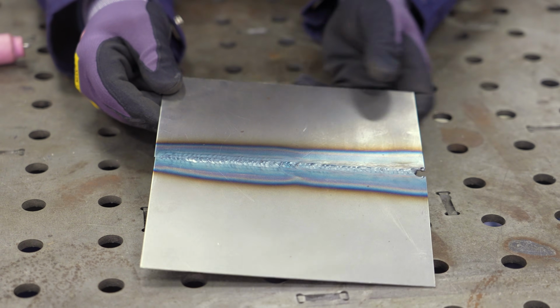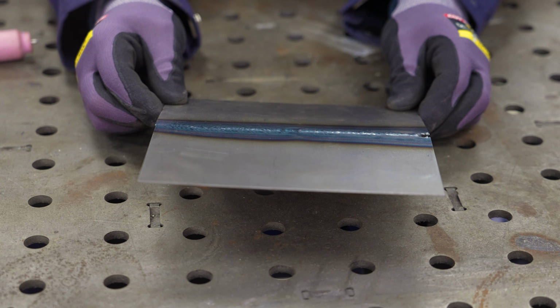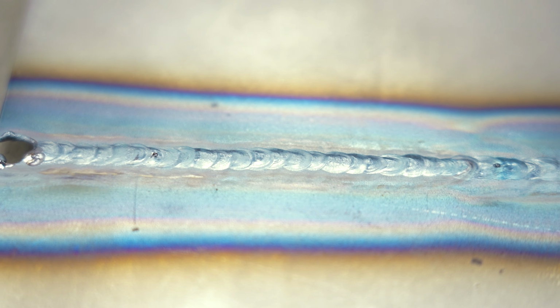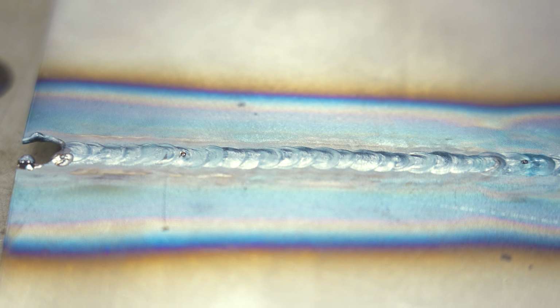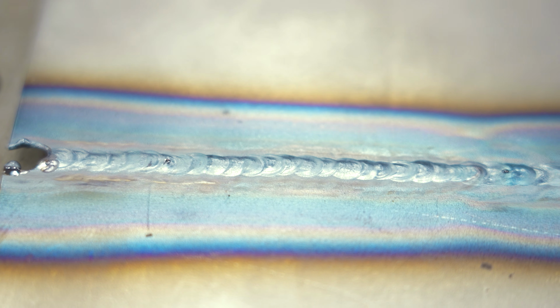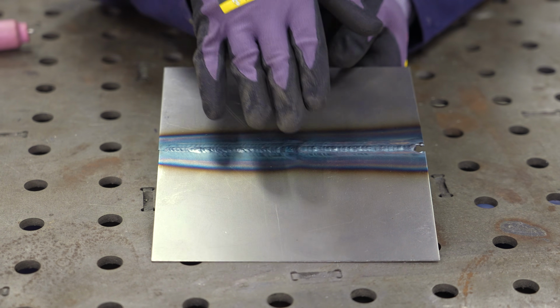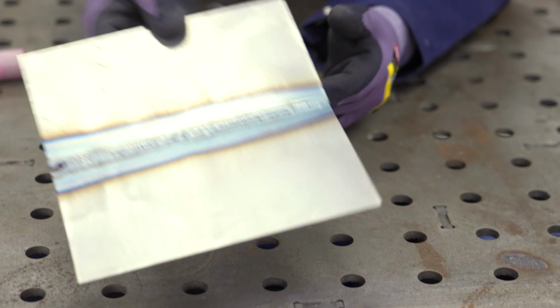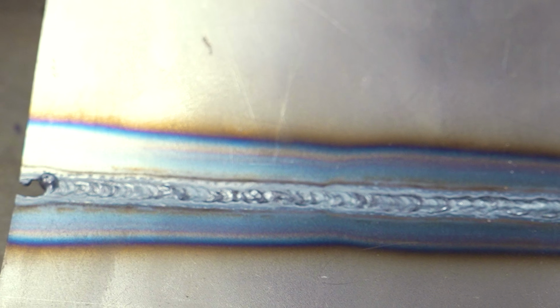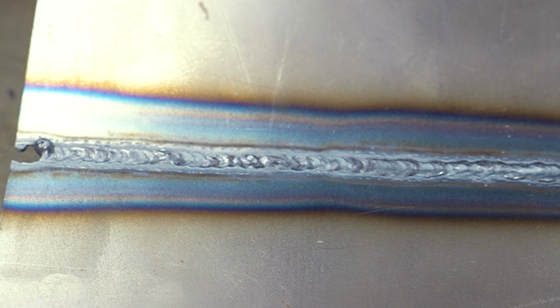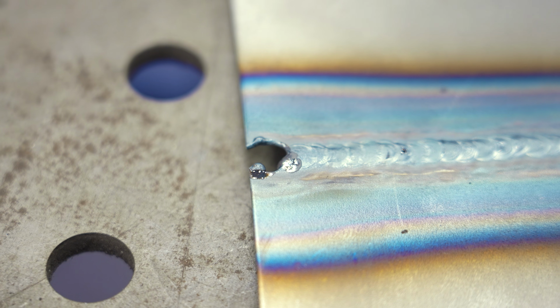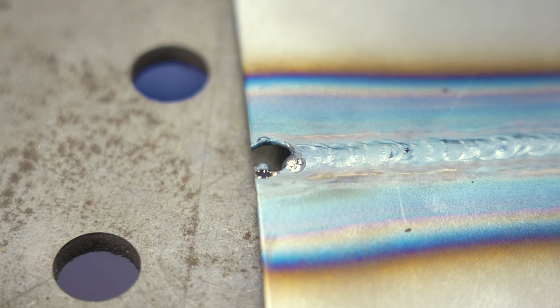So you'll notice first off that this panel is no longer flat. Secondly, you'll notice that my dimes are pretty good. I'd say that I might have had my heat a little bit too high. They could have had a little bit more build upwards because I had a higher heat. I had fairly good, if not incredible, penetration on the rear to the point that, like I said, I blew through on the end, which is not ideal.